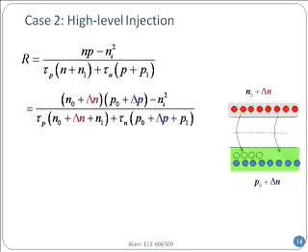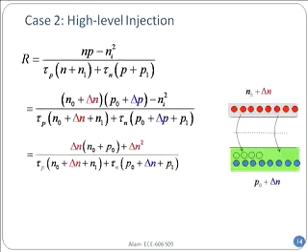You will expand it the same way, but this time, unfortunately, you cannot leave out delta n squared. In fact, delta n squared is much larger than the first term, right? Because ni, let's say, is 10 to the power 10 or so. Delta n, if it is 10 to the power 18, then this whole second term will be significantly larger.